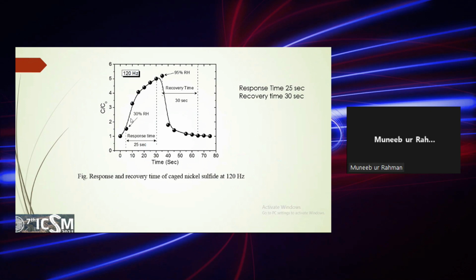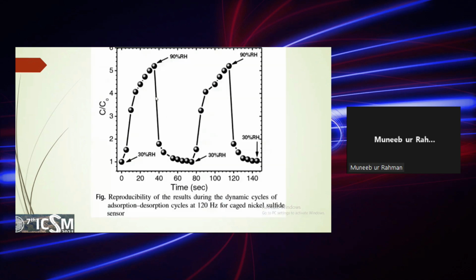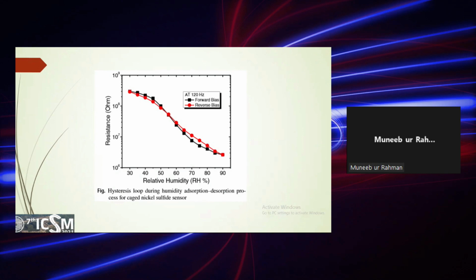So this is the response and recovery time of our sensor. The response time was noted to be 25 seconds, and the recovery time was noted to be 30 seconds. We also repeated this measurement for another cycle to check whether it is repeatable or not. So this is what we did. Our data shows that it is repeatable. Our sensor repeatedly produces almost the same results, so the repeatability of our sensor is very good.